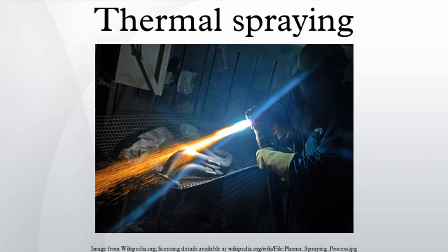The particles flatten when they impinge on the surface of the substrate, due to the high kinetic energy. The particles rapidly solidify upon contact. The stacked particles make up a highly wear-resistant coating. The PTWA thermal spray process utilizes a single wire as the feedstock material. All conductive wires up to and including 0.0625 inches can be used as feedstock material, including cord wires.